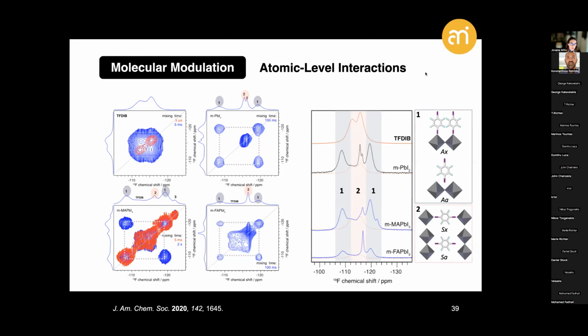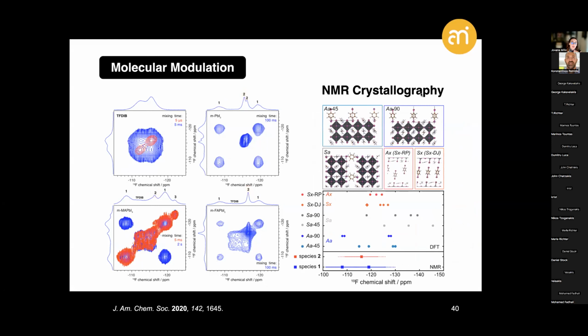Now, having assigned these general binding modes on the surface of hybrid perovskites motivates us to further look into their specific orientation, which involves a number of different configurations and stimulates complementing these NMR measurements with theoretical molecular dynamics calculations and DFT calculations of the corresponding chemical shifts, in an approach otherwise known as NMR crystallography. This enables us to confirm these original assignments, looking into hundreds of different configurations, but also to exclude one of them, being the symmetric binding mode through A-cation cavities, which is in line with the directionality of halogen bonding, and which is done within a level of confidence including errors of both the density functional theory calculations and the NMR spectroscopy, offering us more insight and confidence in the presence of halogen bonding and in the nature of these interactions in hybrid perovskite materials.